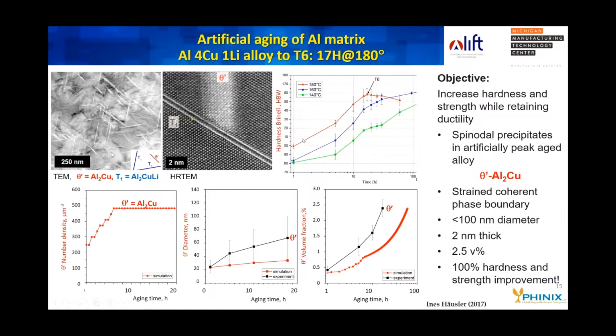And you can see that the microstructure that is produced on peak aging consists of disc-like precipitates, shown in the first picture on edge. And in this particular alloy, there are two types of precipitates, theta prime, aluminum copper, and T1, which is aluminum copper lithium. In the higher resolution TEM picture, the second one, you can see both of them at the same time, and you can see that the theta prime is about 2 nanometers thick, and that the interface of the theta prime and the aluminum matrix is quite coherent.